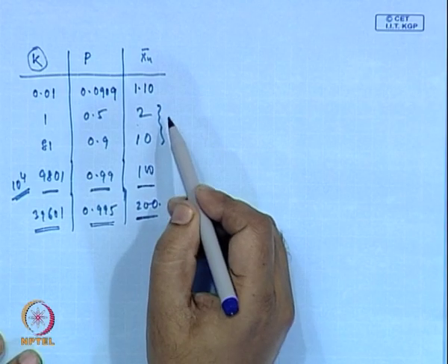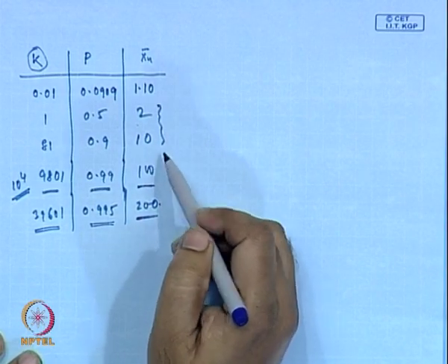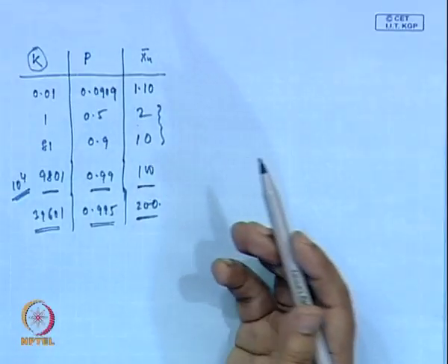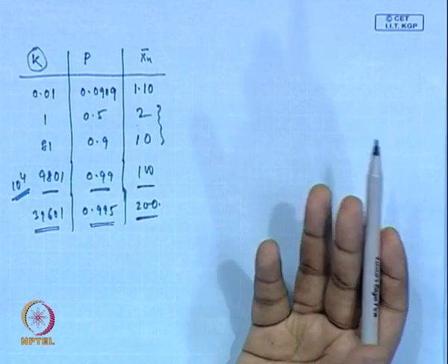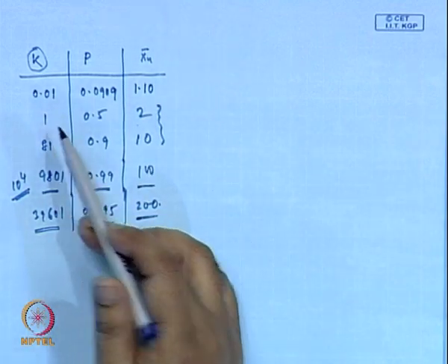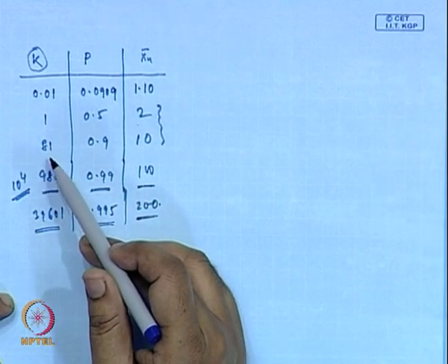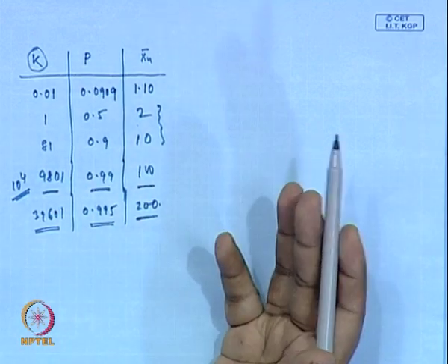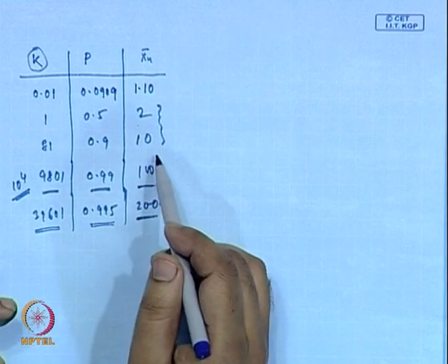If you do not remove your condensate, then your reaction will end up at an oligomer stage, maybe dimer, trimer or tetramer, a mixture of those, but the average will be a dimer for an equilibrium constant of 1, and for an equilibrium constant of the order of 10 to the power 2, it will be at the stage of xn about 10.